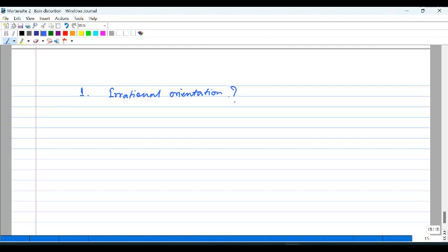Okay. So we have seen that the Bain strain can change the austenite lattice into a BCT lattice, from an FCC to a body-centered lattice. And what have we done in that case in the Bain strain? We have a compression along the C-axis and extension along the other two.